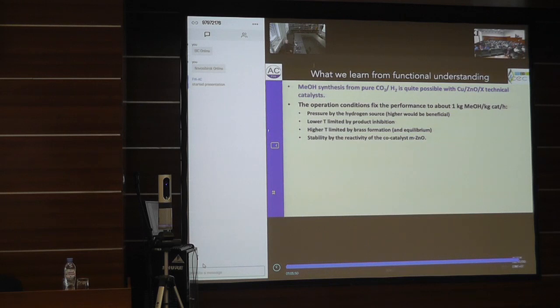This is 30 bars for electrochemical reasons. If you go for higher pressure, then we go also for higher performance. But the 1 kilogram methanol per kilogram catalyst an hour is an absolutely competitive performance when you think of the normal syngas synthesis that has very much the same productivity.